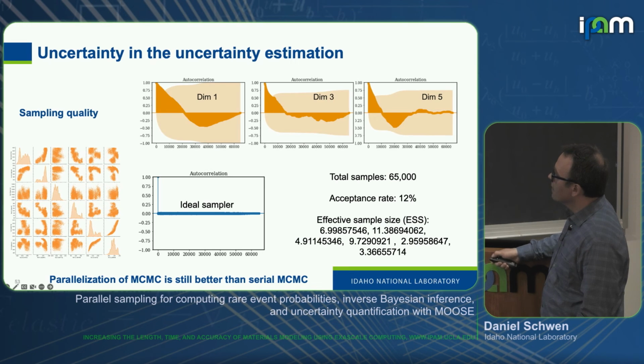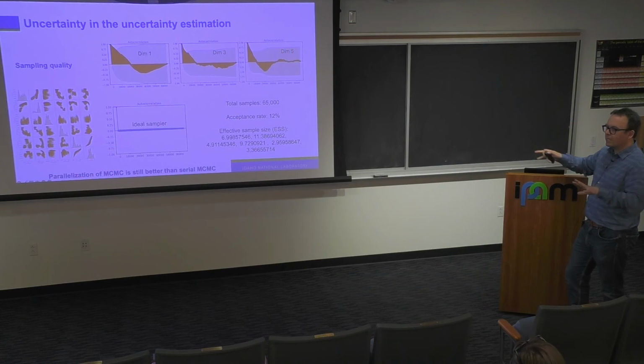But if you look at the autocorrelation between the samples, they are extremely correlated, which results in very low effective sample sizes. So if we had taken only 10-ish completely, statistically independent samples, we would have gotten the same amount of convergence or quality here. So that's obviously not great. An ideal sampler is one where you know the distribution that you're drawing from, and you can just do Monte Carlo, right? Randomly draw, and that has basically no autocorrelation.